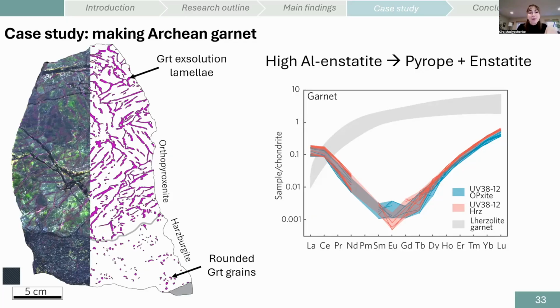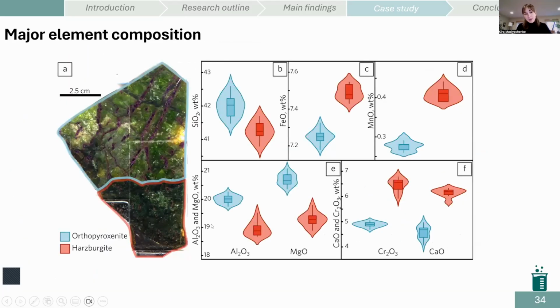But the interesting thing about this sample is that garnets from both parts of the sample, both the fine-grained garnet here and the lamellar garnet on the top, have exactly the same U-shaped, really depleted rare earth element spectrum. That hints at the same origin for both of those garnets, meaning that this garnet can be the product of the recrystallization of the lamellar garnet. But we need to prove that, because those garnets also have very different major element compositions. The garnet in the harzburgite part is more depleted in silica, aluminum and magnesium than the garnet in the lamellar part, but it's more enriched in almost the rest of the elements. We have more calcium, chromium, manganese, and iron in the bottom part of the sample.